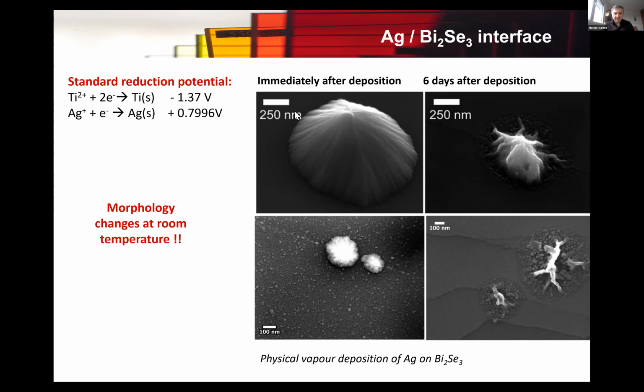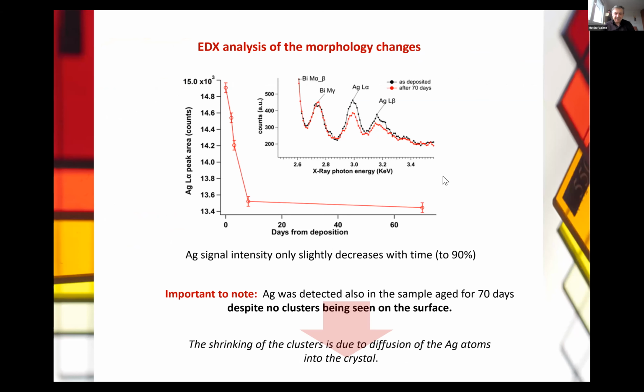So the analysis shows that with time, this is EDX analysis done in the scanning electron microscope, you can see that the intensity of silver is dropping, like here. It does not disappear. Even when we don't see any clusters on the surface anymore, we still see the signal of silver, which tells us that silver does not evaporate or anything like that, but actually it diffuses into the surface, into the system, into the substrate. Now, when we say diffusion, it's just a description. I don't want to prejudge what actually is happening, but this was our task, to understand what this diffusion is. Is this intercalation, or is it some kind of more proper chemical interaction?